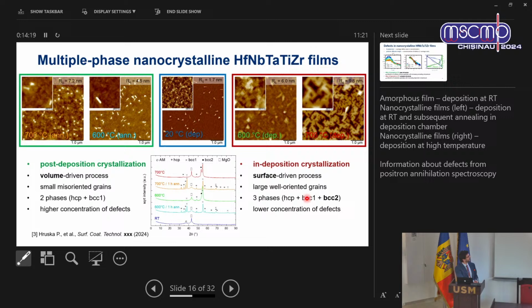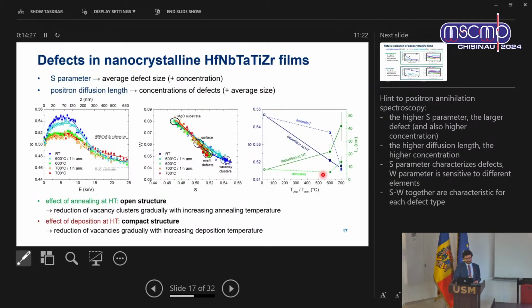If we have a look at the defects, in this case, I present the results of the second method of the Doppler broadening. But again, just a quick review, we observe two quantities. The S parameter reflects more or less the average defect size, and the diffusion length of positrons reflects their concentration. So in the first plot, you can see that if we go from the amorphous film with the really largest defects to the films deposited at high temperatures, we are tuning the defect structure. We are slowly removing the vacancy clusters to the limit where we have only vacancies present in our films. And also, by further increasing the temperature, we can even, by increasing the diffusion length, reduce their concentration. So the temperature allows us really to control which open structure we want to have in our films.